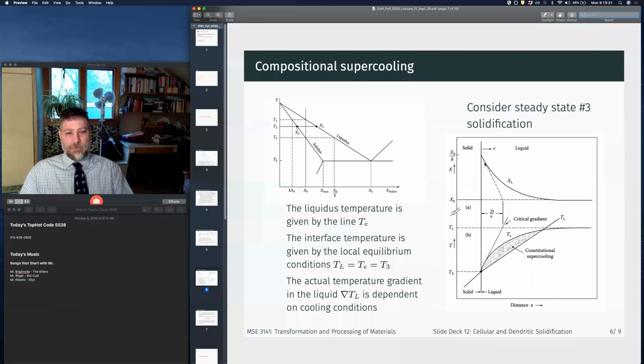When we talked about the Scheil equations, we said we had perfect mixing. What's the case going on here? We don't have perfect mixing anymore. This is solute being rejected at a decreasing rate as it goes on. So we have diffusional mixing in the liquid, and it takes time for the liquid composition to homogenize. So we've got this pileup region that has a characteristic width to it.